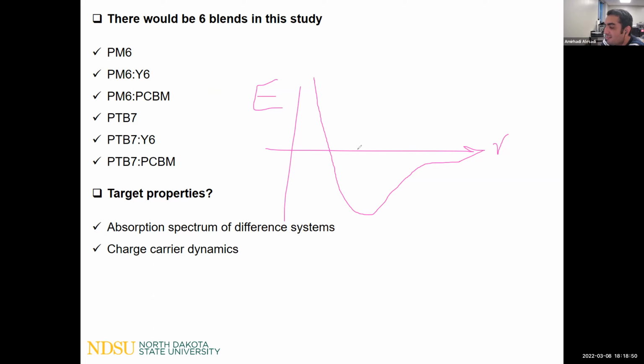The system will try to reach the minimum energy of the non-bond interaction here. So this function, for instance the 12-6 Lennard-Jones potential, is defined for non-bond interaction. Other force field parameters, for instance bonded potentials, follow almost the same behavior in the system.